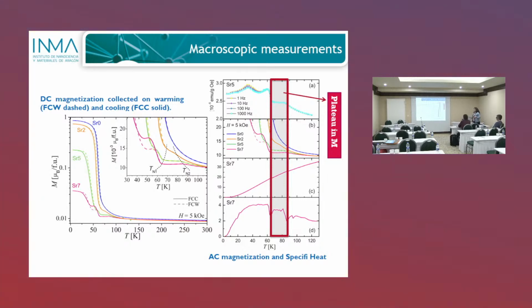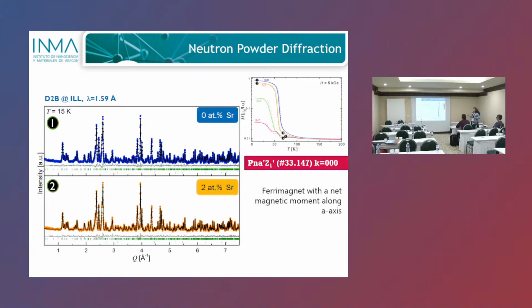And in that region where it gets flat, you have some features in the specific heat. So there's something going on there, and we wanted to see what was happening in this region. For this, we did neutron diffraction experiments. So in order to see the difference on what was going on in that temperature range, we needed to first be sure that the low temperature state was as expected, and what is as expected.